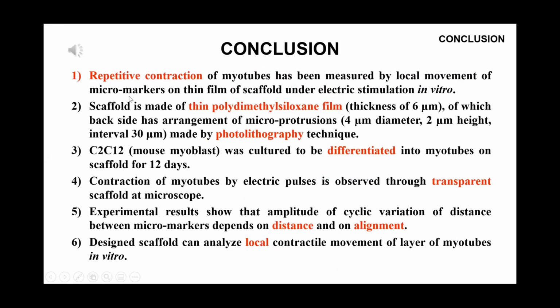Conclusion. 1. Repetitive contraction of myotubes has been measured by local movement of micromarkers on thin film of scaffold under electric stimulation in vitro. 2. Scaffold is made of thin polydimethylsiloxane film of thickness 6 micrometers, of which the backside has an arrangement of micro-protrusions of 4 micrometers diameter, 2 micrometers height, interval 30 micrometers, made by photolithography technique.